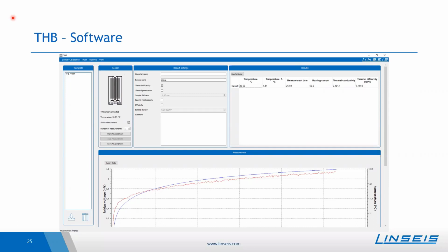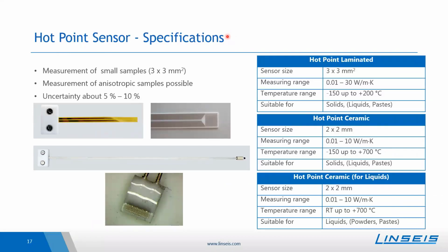The next question which came up is what portion of the hot point sensor should be covered by the sample? I have mentioned that the hot point sensor is especially suited for small samples. So only 3 times 3 millimeter squared samples are necessary. The thickness here should also be at least 3 millimeters or higher, depending on the thermal conductivity. Here on the tip are the measuring wires. So here it's a little bit closer. For the ceramic version, only this portion should be covered. Here only the front part, the same for the laminated version, and the same also for the ceramic version for the liquids.